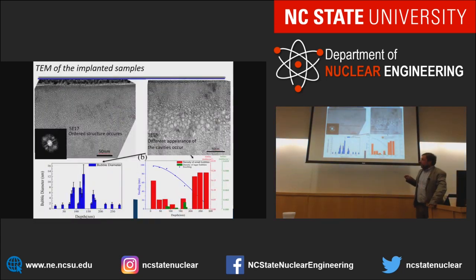Now in the transmission electron microscope, that takes a lot longer. You see, of course, your helium implants, the helium bubbles in your material. Interestingly, the helium bubbles are not random. They have some sort of structure to them. If you take that image and calculate a fast Fourier transform from it, you find there are peaks. Those peaks say there's an order to those helium bubbles, called the helium bubble superlattice. It was found in the 70s and 80s. If you do a higher dose implantation, your bubbles get a lot bigger, not surprisingly. And so now we can measure the bubble density and calculate the swelling derived from the images.